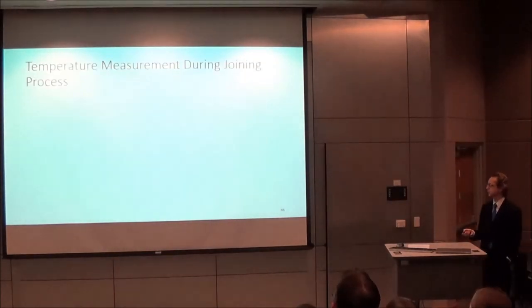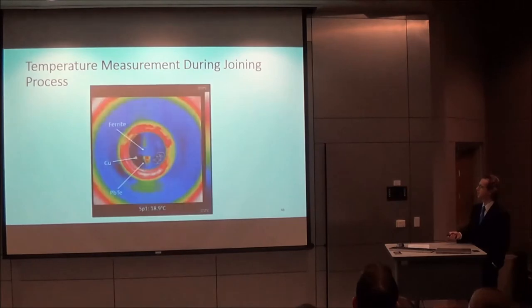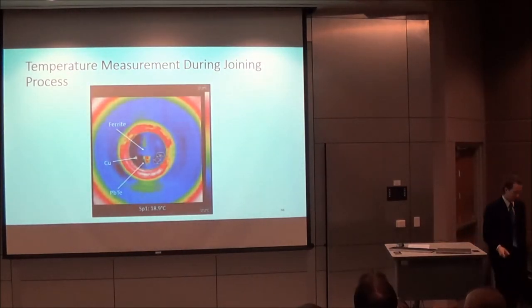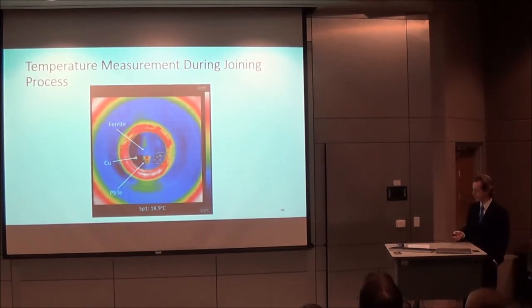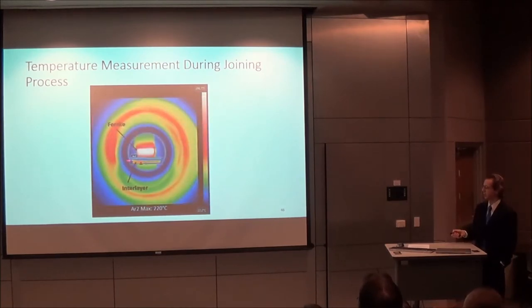The results of the solder joint will be discussed next. The temperature measurement was performed using a FLIR T300 thermal camera, which was situated above and looked down through a tube into the waveguide. Here is the ferrite material. This is an image shot at the very beginning of the experiment before the microwave was turned on, showing the copper-based material and then lead telluride. At the point of melting of the interlayer, this picture was captured, and it shows that the ferrite is significantly hotter, and the heat is being transferred to the interlayer where it is melting.